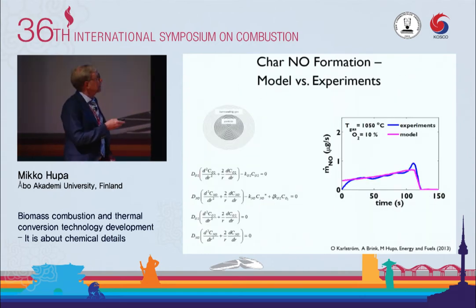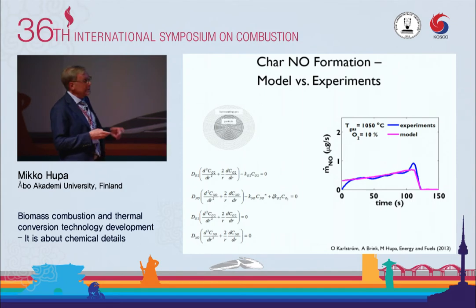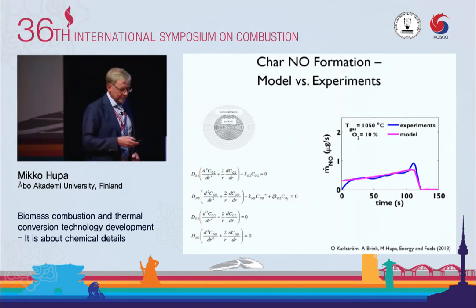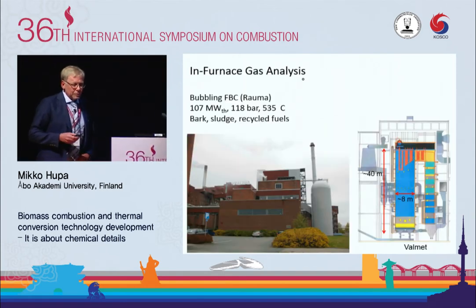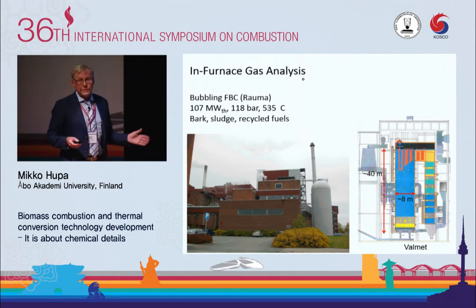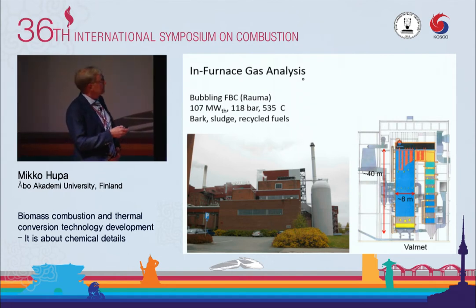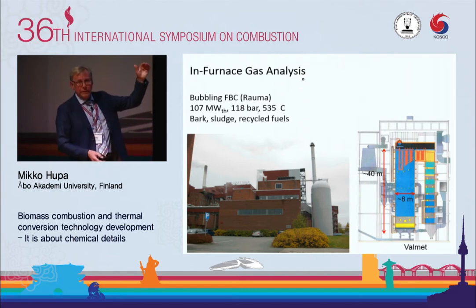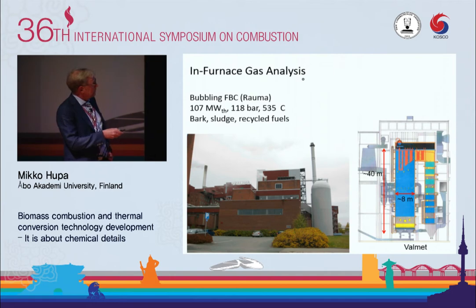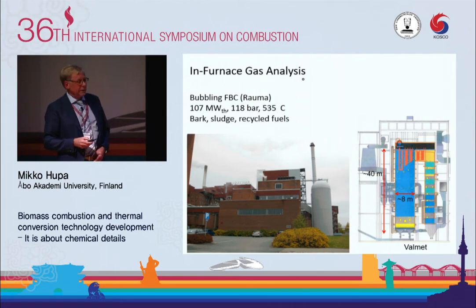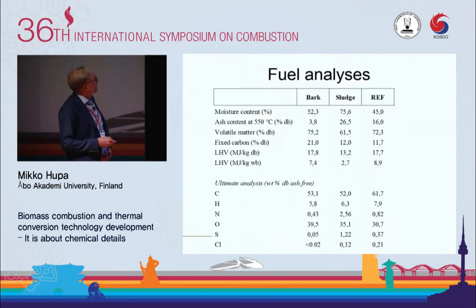We can model it, we can produce a standard model, and if we take into account the diffusion of NO and oxygen into the particle, we can create a model which reproduces nicely this phenomenon. But what was more interesting, we did tests in a large scale unit. This is the unit. It's a fluidized bed with a big freeboard. You see almost 40 meters, and we wanted to try to sample inside such a furnace and see how nitrogen oxide is formed. This was the topic.